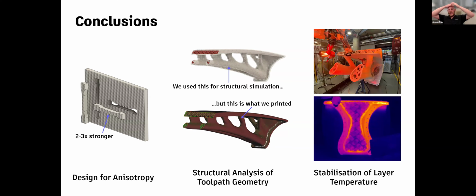And then the big issue that we ran into was stabilization of layer temperature. On this print, we had included an infrared temperature sensing system at the edge of the extruder. So we're running 3 heat bands. The pellets are running through a dry air system coming to the top, getting pushed through the screw. And then we're watching the temperature as it's coming out of the nozzle, so as the layers are being deposited, and then the temperature of the previous layer that's getting covered over, because there's a narrow range of temperatures that you want to stay in to get good layer adhesion, and we were worried that we might be getting too hot, and that we would need to slow the robot down. So we wrote a script so that the robot would slow down if the layer temperature difference was too high.